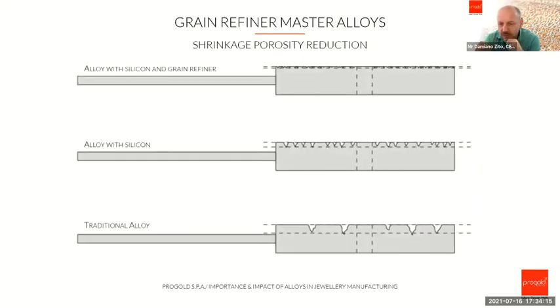So the trick is not that there is a different shrinkage, but that the shrinkage is much more distributed and stays much more on the external part of the object, very close to the surface. And a small amount of grinding is able to remove them.